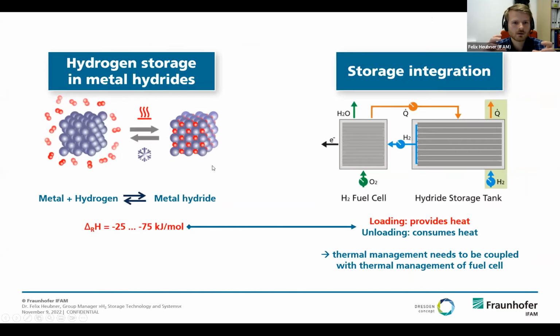Again, combining this thought about reaction enthalpy: absorption is exothermic, desorption is endothermic. You always need a heat source available for a hydride application. So every material needs to be integrated into an energy system because you need waste heat. That's just one example, a very schematic drawing, having a fuel cell in operation on the left-hand side, fueled from a hydride storage. Heat needs to be transferred to the hydride storage to release hydrogen again. So it is possible to integrate one third of the exhaust heat of a fuel cell to the hydride storage to release hydrogen.